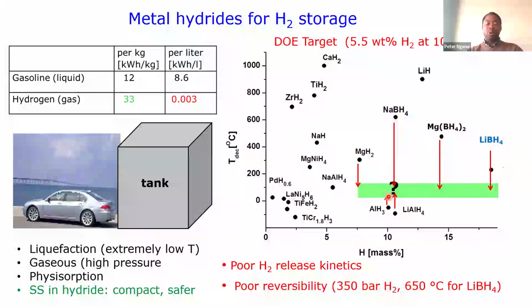Also, all these ones. And if you look at all these other ones, like alane, which is a very interesting one, you see that it's thermodynamically unstable. And also the same thing with lithium alanate. So, nature doesn't give us a free lunch, so we always have to find a way to use what nature has provided to get the lunch, right? So, how can we now begin to play with thermodynamics, to shift all this attractive material into this temperature window? And another problem with this material is that when you have released hydrogen from them, it might be difficult to take the hydrogen back because the reversibility kinetics is quite poor.